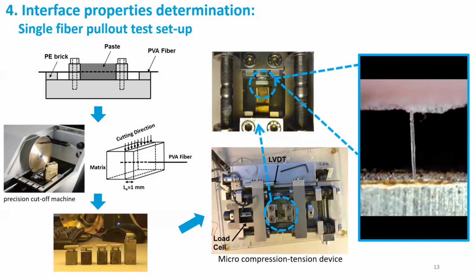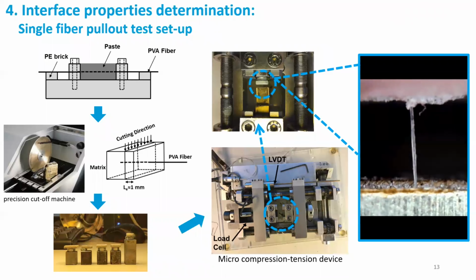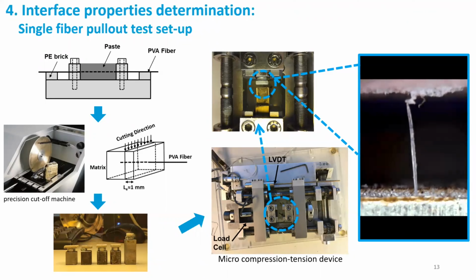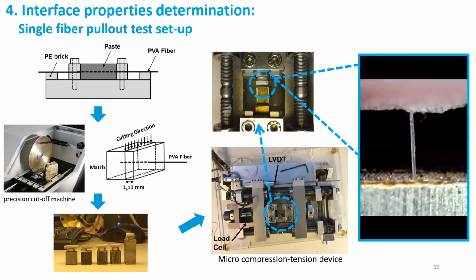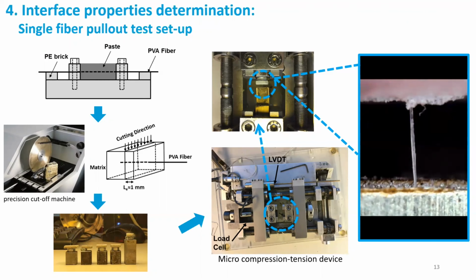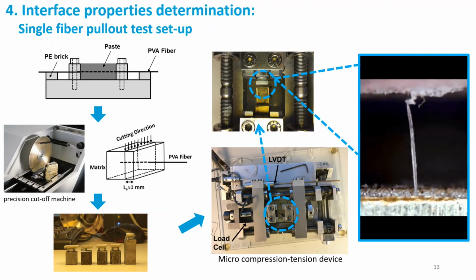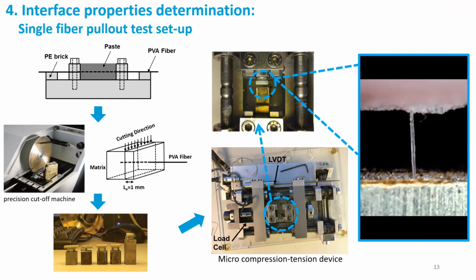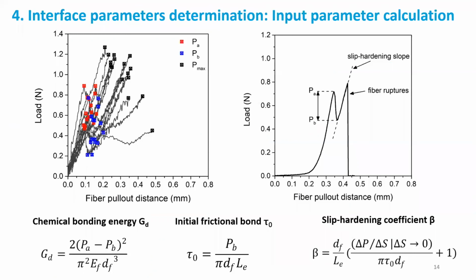And also we determine the interface properties using the single fiber pull-out test as shown here. We are using a precision cut-off machine to cut the fibers and the specimen into very thin slices, and we are using a micro compression tension device to pull out the fiber as shown in the video. So here shows the results from the single fiber pull-out test. And from these results, we can calculate 3 very important interface inputs, which are the chemical bonding energy, G_d, initial frictional bond, tau 0, and also the slip hardening coefficient, beta.